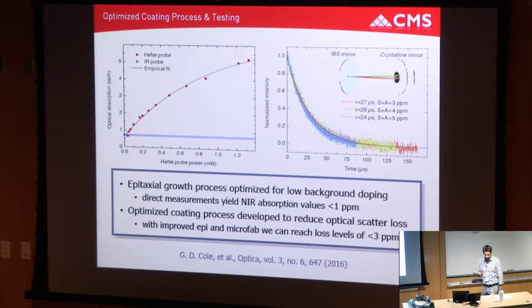The one thing we fight with: there's two growth processes for doing these epitaxial arsenide structures. There's MOCVD, metal organic chemical vapor deposition, or molecular beam epitaxy. With MOCVD, the problem is the MO, the metal organic. There are these long organic molecules with carbon backbones, and the carbon ends up being incorporated in the gallium arsenide. That's a p-type dopant, an acceptor in gallium arsenide, and it absorbs fairly nastily for us. So we have to stick with MBE.